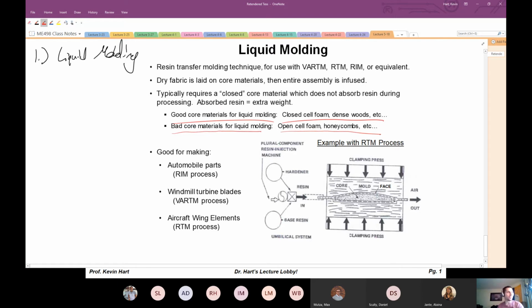All right, if you have an open cell foam, then the resin is just going to penetrate into that foam and give you a significantly heavier core than what you want. All right, honeycomb structure, you could just fill the honeycomb spaces with resin and then you just have a super heavy core. What is the point of that? All right, so you can't really use this process for anything that has open cells in the center. Right?